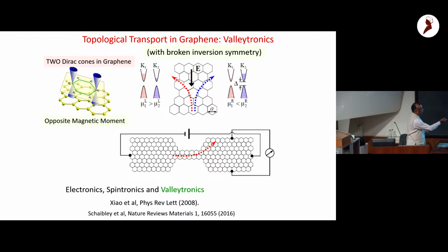Because there is no Hall voltage which gets developed, because both are negatively charged electrons. So to differentiate between valleys, you have to use circularly polarized light to excite electrons selectively, because the chirality in the two valleys is opposite. And that's how one can access it. But this is a very simple effect I can demonstrate as a consequence of just this interesting quantum geometry.